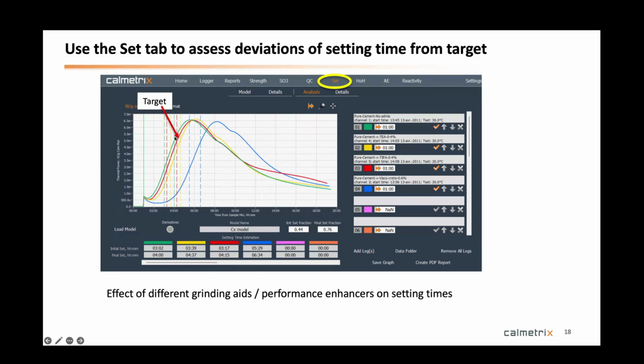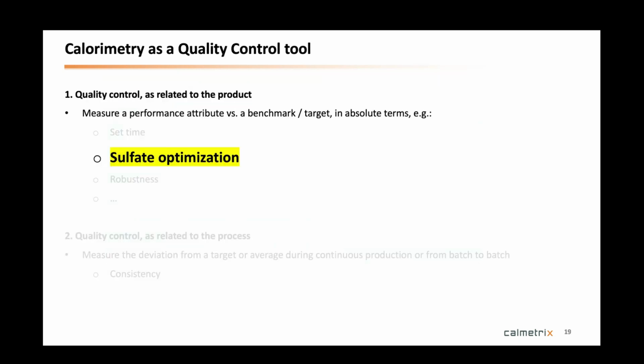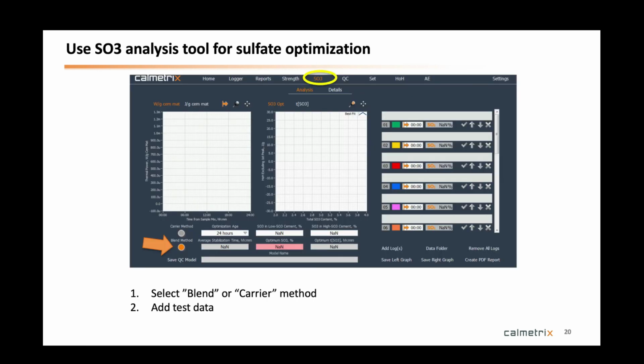So it's a good quality control tool, both visually from the perspective of a qualitative assessment, as well as quantitative, because you do actually have estimates of initial and final set here on the bottom. So that's a good tool for that, and a lot of people have used it, so it's not so new. Sulfate optimization, the same. We actually have a ready-made software for that. It follows the standard, ASTM C563.